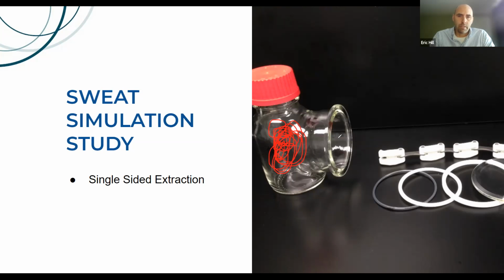And then we would usually do that extraction again under 40 degrees C temperature for the maximum use time of the patch. And so if the patch is adhered for a maximum of an hour a day, we'd extract for an hour, again under 40 degrees C, which mimics that exercise temperature that the patch is going to see.